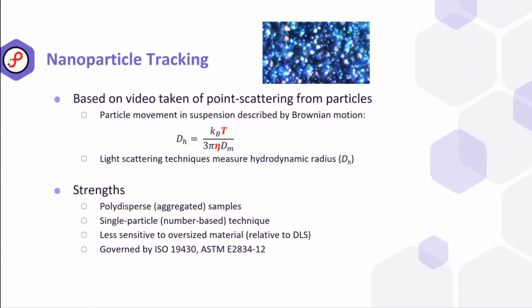And what you see here is kind of a really saturated image of a bunch of particles floating around in suspension that are scattering a number of different incident laser beams. And what we can do is watch these particles move through suspension by tracking the light that's scattered off of them. And that's really what the experiment is. It's very similar to DLS, except in this case, it's a single particle experiment. Now, what that allows us to derive is the diffusion coefficient, and combined with the temperature that we've done the experiment at and the viscosity, we can directly calculate the hydrodynamic radius or hydrodynamic diameter of that particle. And all that really means is we're assuming it's a sphere, and then there's probably some solvent stuck to it. But it's a very good measure of that nanoscale particle size in these suspensions.